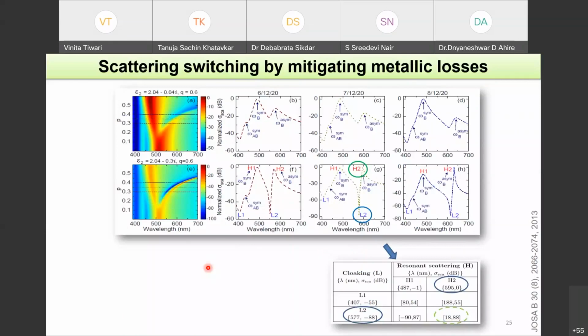You put some quantum dot inside the dielectric layer so that there is some gain. So in that case, you find this kind of compensation, and you will see that you are able to restore those high peak and low dips. So let us take one example here, L2 and H2. You can see H2 happens at 595 nanometer wavelength, and the normalized scattering is 0. And L2 happens at 577, and the normalized scattering is minus 88 dB. That means with just a change of 18 nanometer of wavelength of the incident light, you can get a contrast of high and low scattering state by 88 dB.